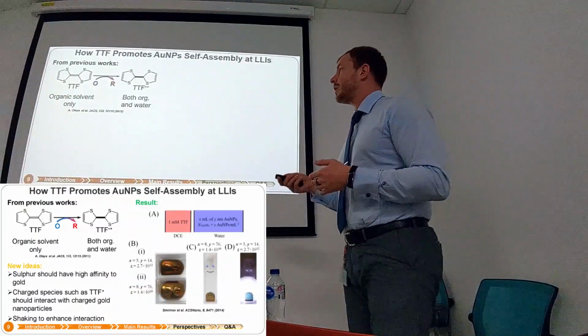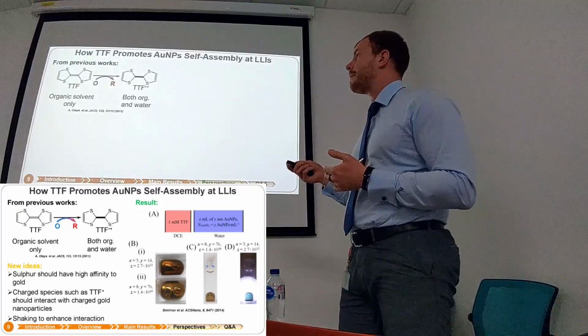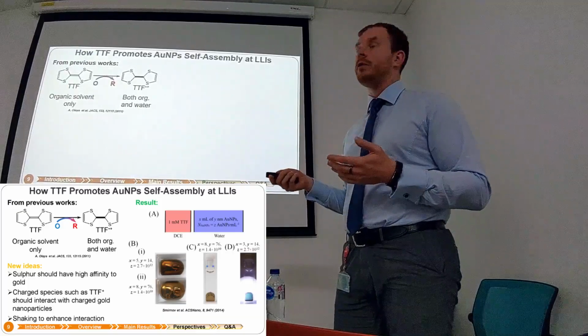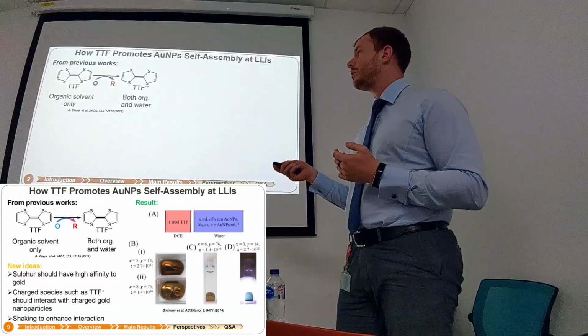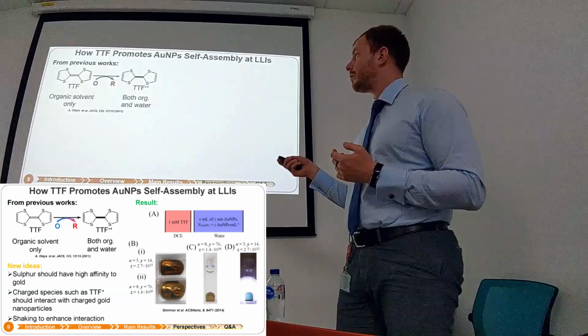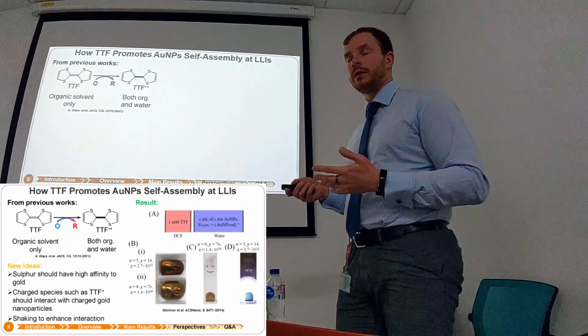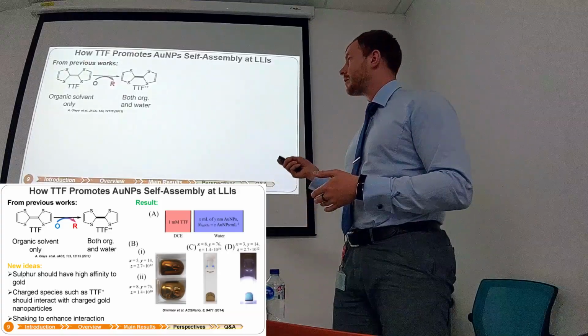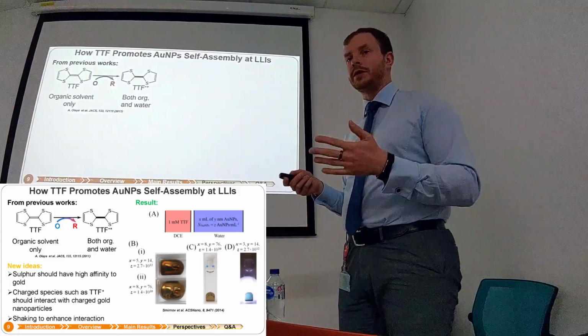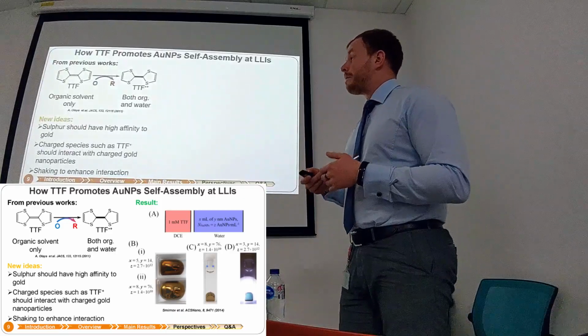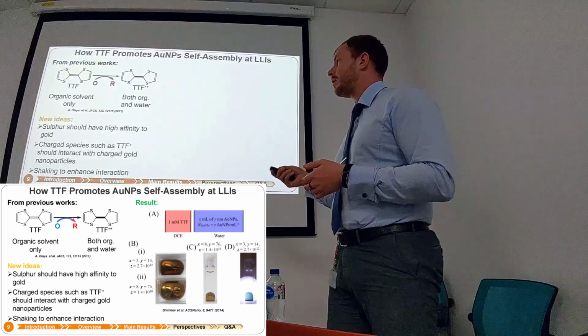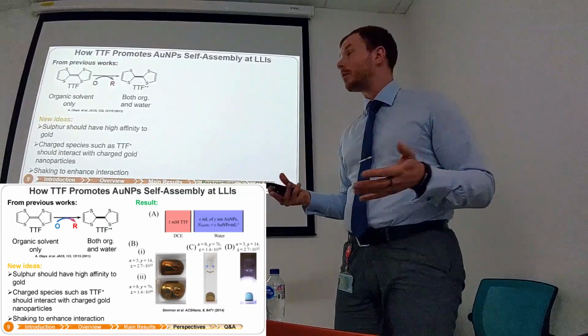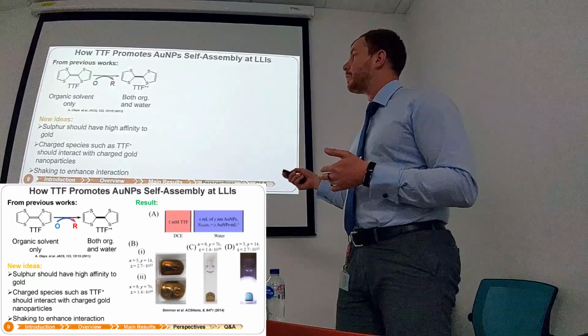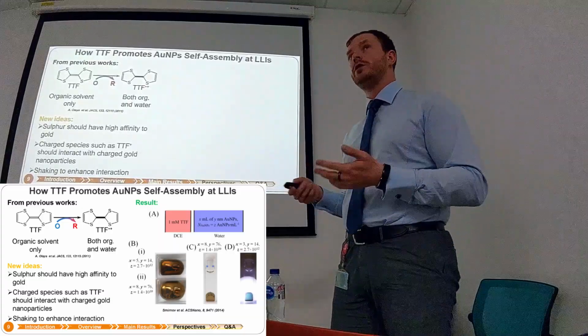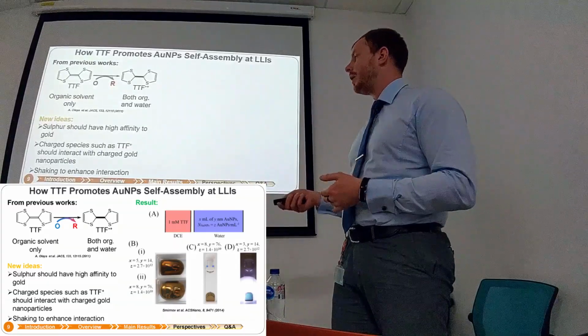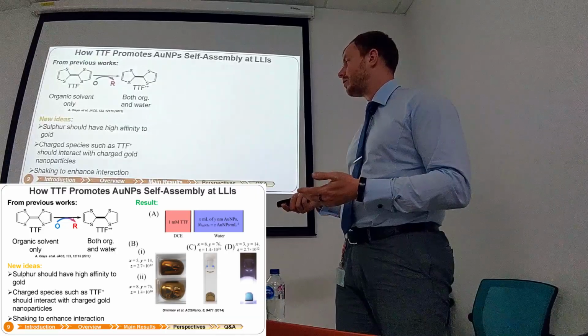Again, when I came, there were several works on this molecule, TTF, that can be dissolved only in organic solvents, but if you oxidize it, you form a cation radical, and this cation radical can already be dissolved in both phases, organic and water. The idea was pretty simple. Okay, it has a lot of sulfur, so let's try to use it to assemble gold nanoparticles. Also, we should form some charged species, so it should promote the assembly. Fair enough. And maybe we need to add some shaking to increase the interaction.